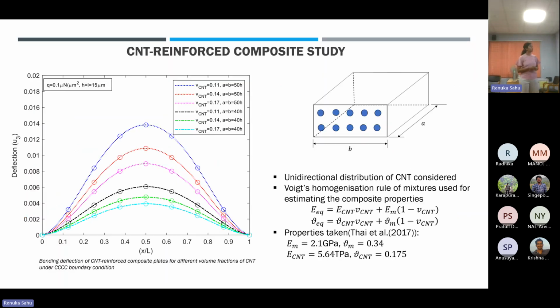We have applied this model to a CNT-reinforced composite study, wherein a unidirectional distribution of carbon nanotubes is considered, and a Voigt's homogenization rule of mixtures is used to estimate the composite properties, with the following properties taken. Here we take two different cases for A by H, the plate width to thickness ratios, 50 and 40.